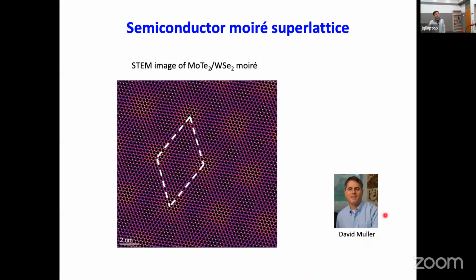This is a collaboration with David Muller's group at Cornell. This is a TEM image of another heterostructure, molybdenum telluride on top of tungsten selenide, and the small dots there, maybe not super clear here, are the real atoms of the original material. Then you can also see the interference pattern that produced this Moiré heterostructure. And because the lattice mismatch generates this Moiré superlattice, it's quite robust. You can see hundreds of these sites forming a quite regular periodic lattice.